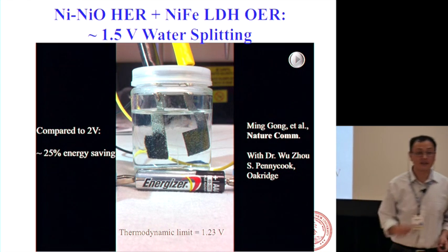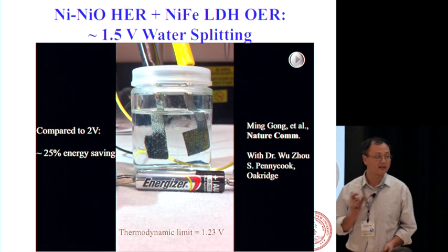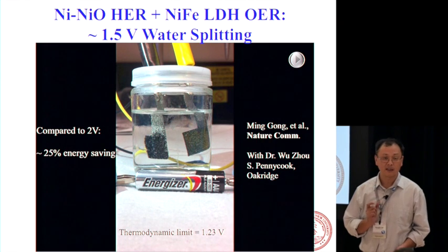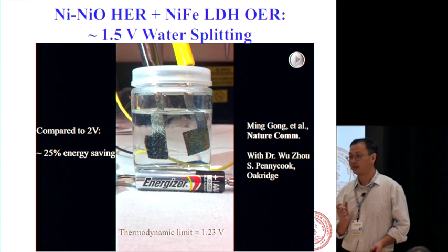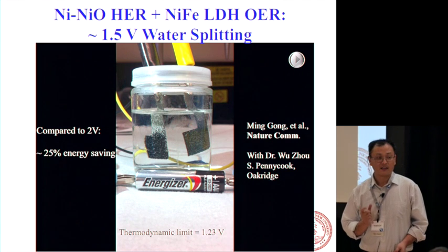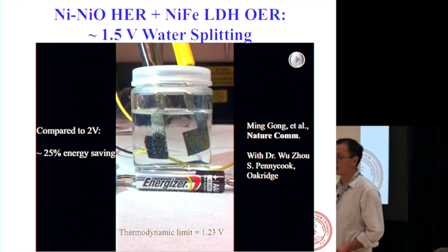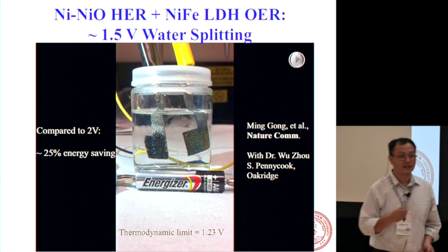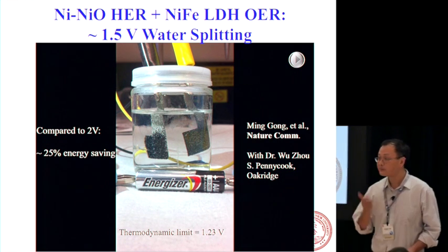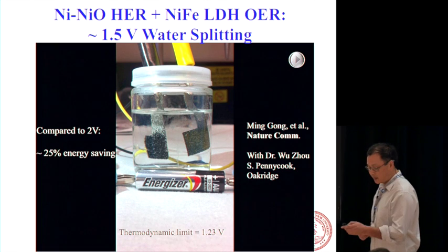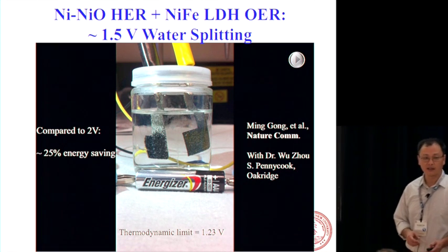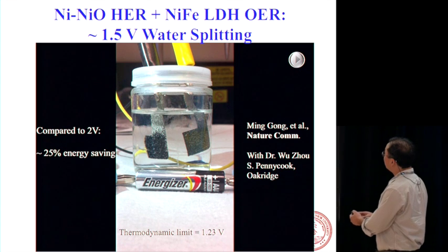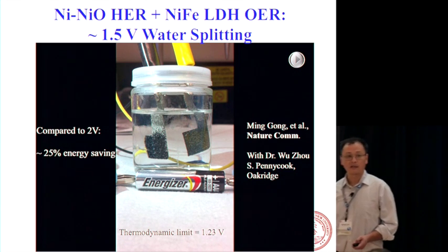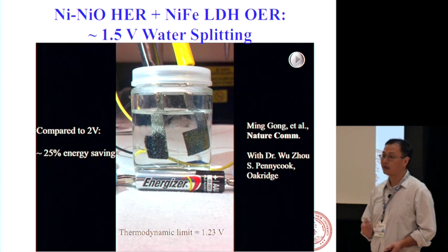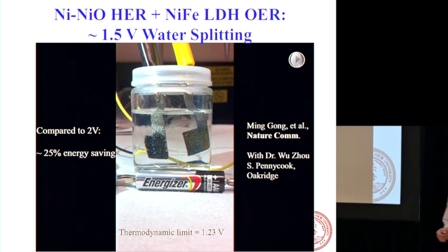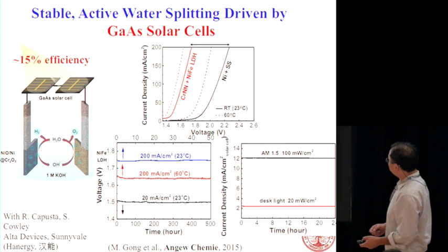Yes. So this is now driven by only a single alkaline battery. It's 1.5 volts, which is not easy to do if you do it at home. Typically, you would need at least 2 alkaline batteries to get to about 3 volts. Then you will see a lot of gas bubbles. And this is good because you're using a very low-cost catalyst, nickel oxide and iron. It's a very active and very stable electrode material.